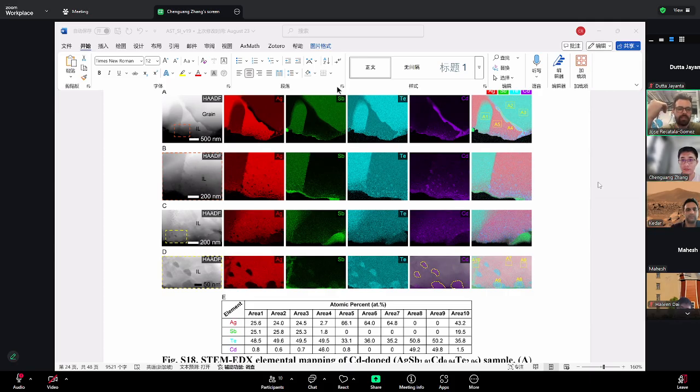Make a caveat, just mention that this is all EDS and therefore it's not absolute numbers, but you can compare within your own samples, which is the point, I think. If different stoichiometry is, I mean, not quantifying the amounts. This is elemental. We want to have phase. If it is stoichiometric phases to identify it differently, yes. This is why I thought EBSD was better, giving you different elements, right?